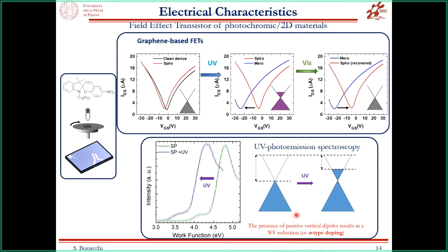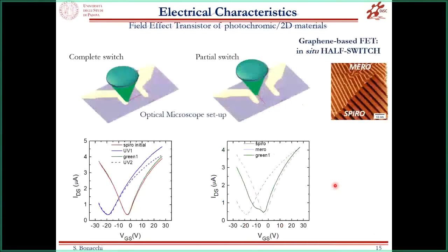And to confirm this result, we also perform UV photoemission spectroscopy in order to estimate the work function of the two molecules, the spiro form and the mero form, and to confirm the doping effect we observed in the field effect transistor with photoemission spectroscopy. So for the first time, we observe a photoswitchable n-type doping of a 2D material just by playing with molecules, and it was also very interesting, at least in our opinion, the possibility to use an optical microscope setup to decide how much we want to change the electrical properties of the thin flakes.